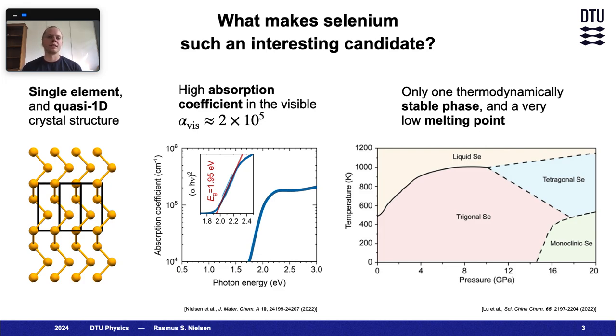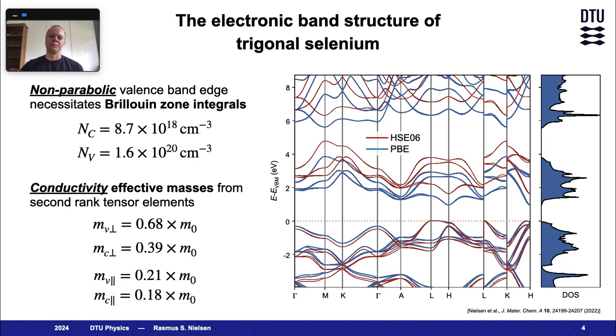Well, first of all, it doesn't get more simple than an elemental semiconductor. We just need selenium, which is not considered a critical material. In its crystalline phase, selenium grows in these helical quasi-one-dimensional chains and exhibits the wide bandgap that we're interested in with a very high absorption coefficient in the visible region. Finally, it's super easy to fabricate. There is only one stable phase at standard conditions, and the melting point is very low, making it not only compatible with silicon bottom cells and easy to work with, but potentially also really cheap to fabricate.